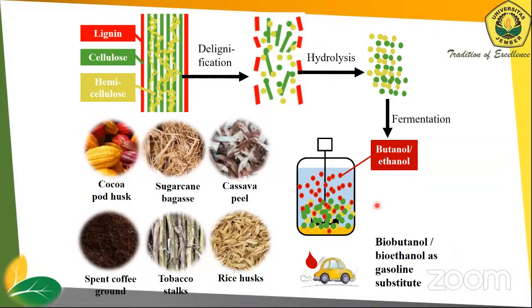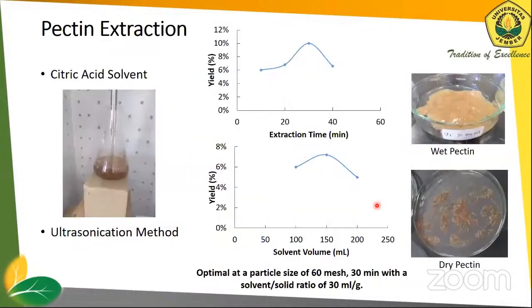Now, this is the pectin that we obtain from the cocoa pod husk. We use the ultrasonication method, and here we can see around 10% yield of the pectin. 10% out of 12% pectin composition in the cocoa pod husk. This is the wet pectin and this is the dry pectin. We use ultrasonication. This is a low temperature process. Then after that, the remaining solid of the extracted cocoa pod husk,